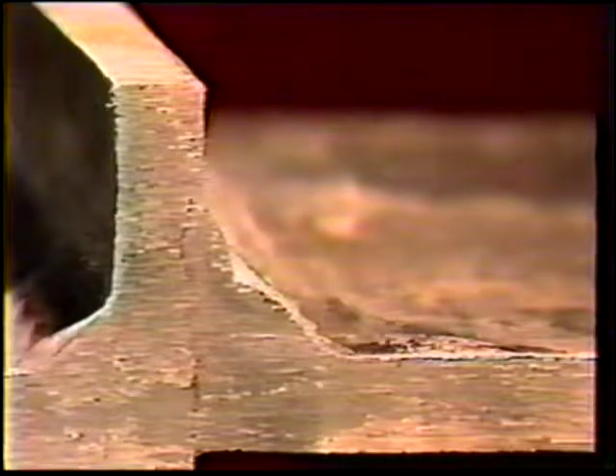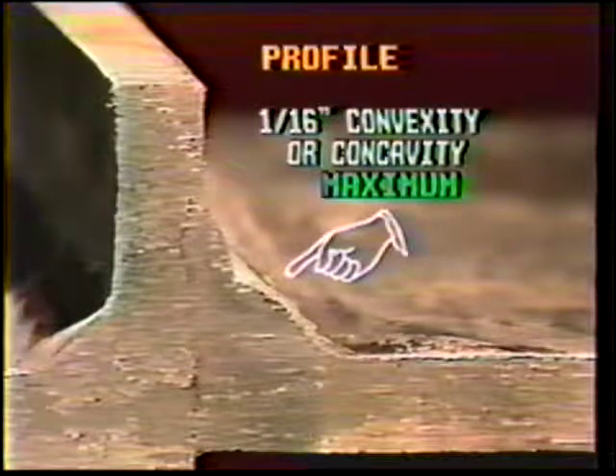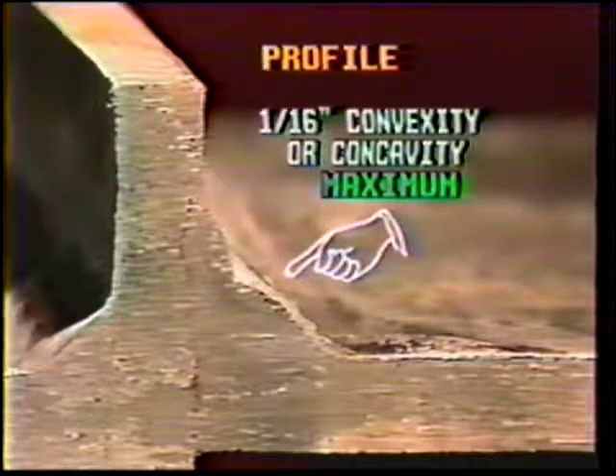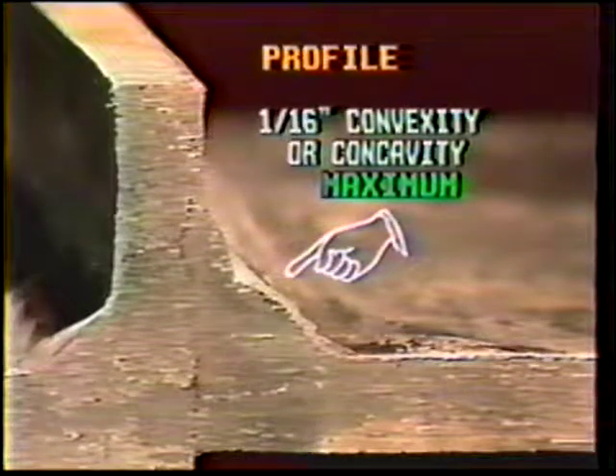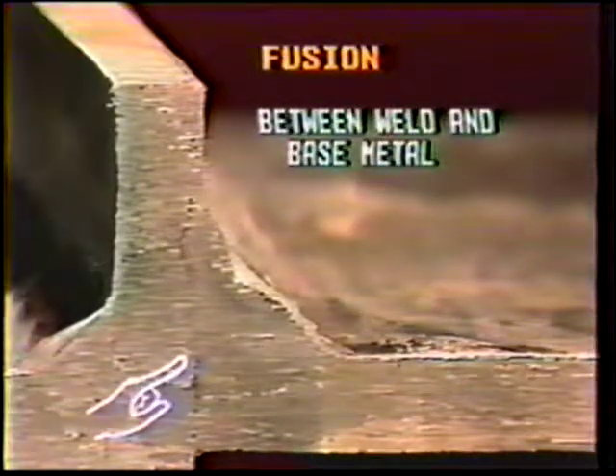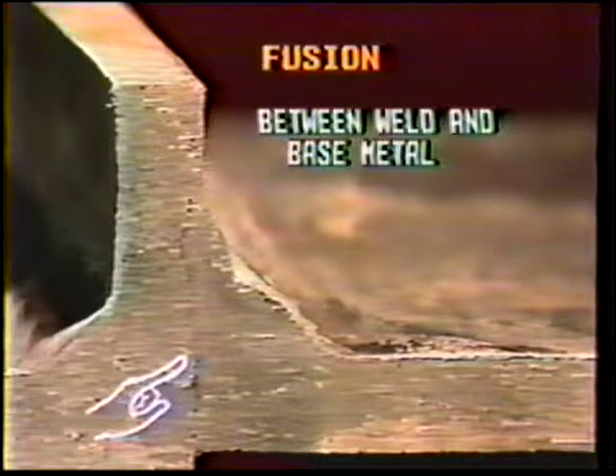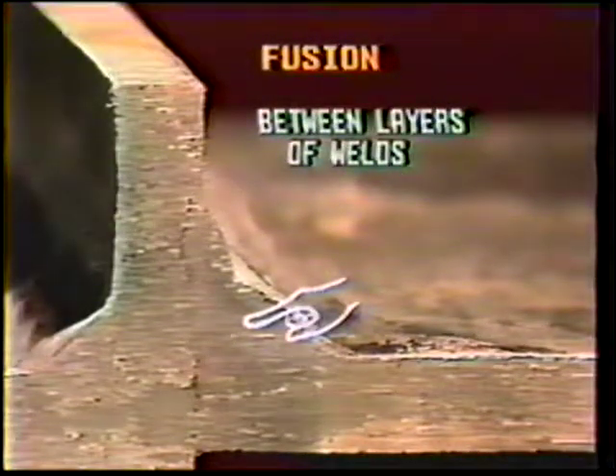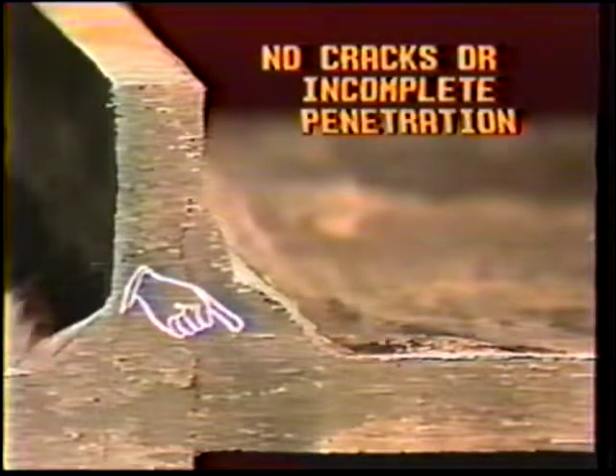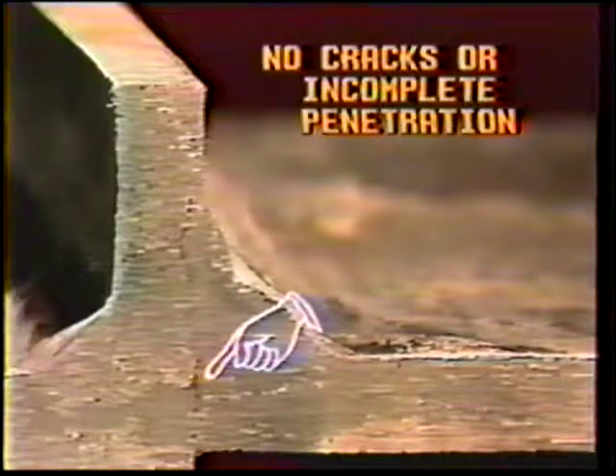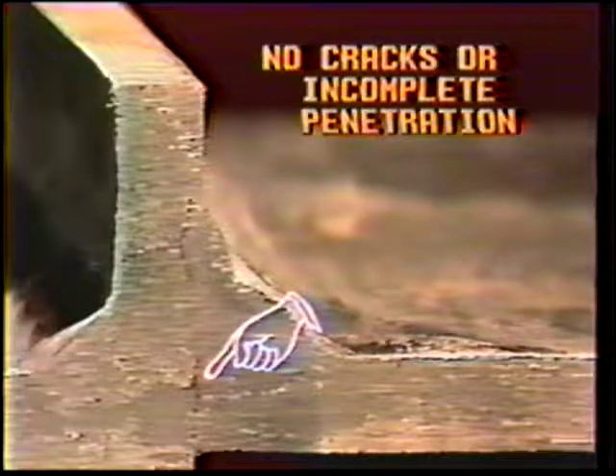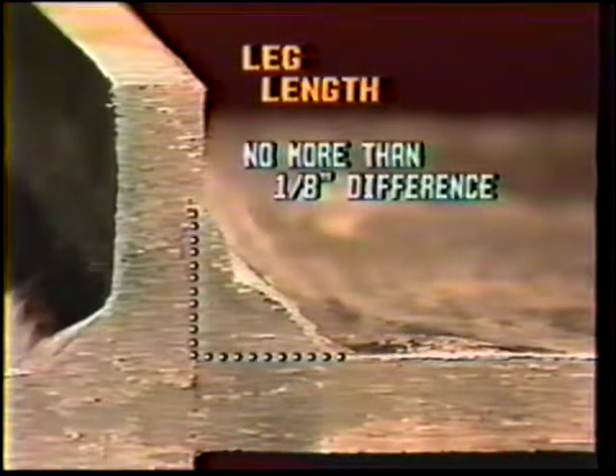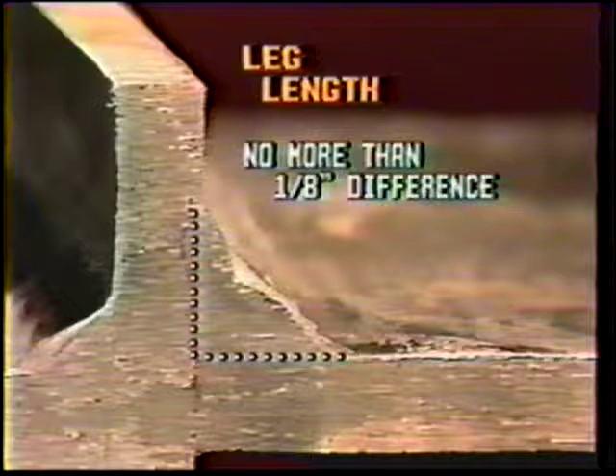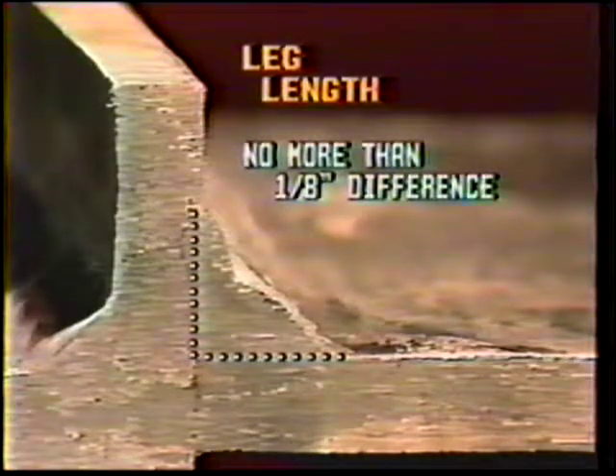The standards of acceptability are: the profile of the weld shall show no convexity or concavity greater than 1/16 inch. There shall be thorough fusion of weld metal and base metal, and between adjacent layers of weld. There shall be no sign of cracks or incomplete joint penetration. And there shall be no more than 1/8 inch difference between the length of the legs. Inspect the results and check with your instructor.